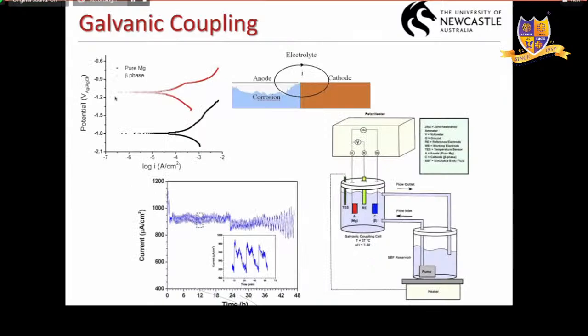As expected, the intermetallic was quite noble relative to the matrix. The matrix is pure magnesium, which has a very highly negative potential, and your beta phase is quite positive. So if the magnesium dissolves, the beta phase is protected. So we joined them together to see the galvanic effect of these particles. We did it using an electrochemical setup. We connected a zero resistance ammeter and measured the current produced from this.